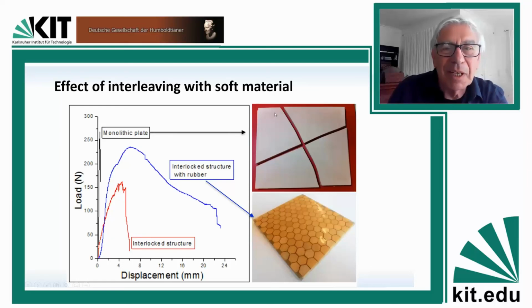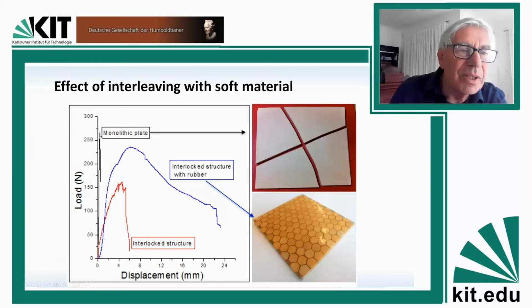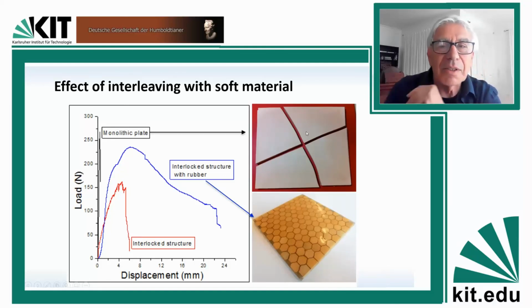And look what happened. If we take the base material from which the structures were produced and deform them under concentrated load, just loading in the middle, you get catastrophic fracturing, catastrophic failure. And this is this curve here, which we already saw. Load displacement: elastic behavior, high load bearing capability, but a catastrophic failure in this fashion.